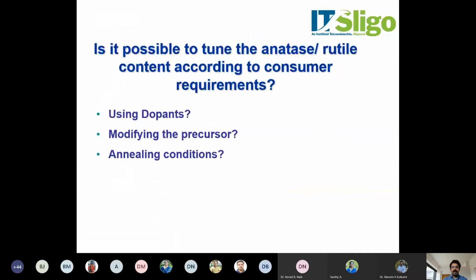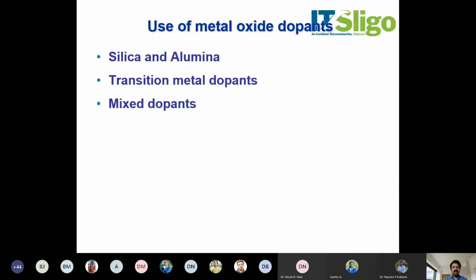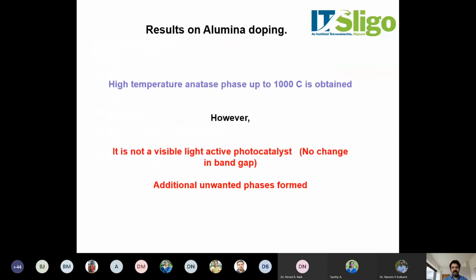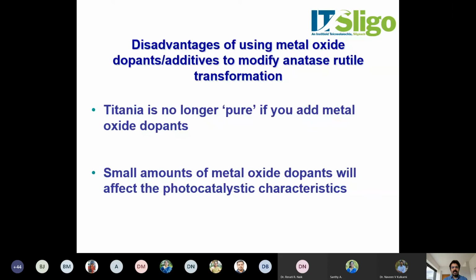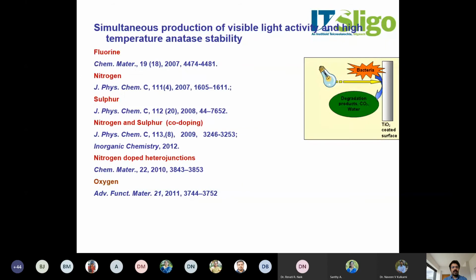So we have done a lot of fundamental studies. We used silica, alumina, a number of materials, and they are stable up to 1000 degrees Celsius, but because of the nature of alumina or silica, titanate is formed, and the photocatalytic activity is not great for these materials. So titania is no longer pure if you add metal oxide dopant. So we have added a number of non-metallic dopants, or what we call anionic dopants, and some cationic dopants into the titania. That is how you can improve the photocatalytic activity.